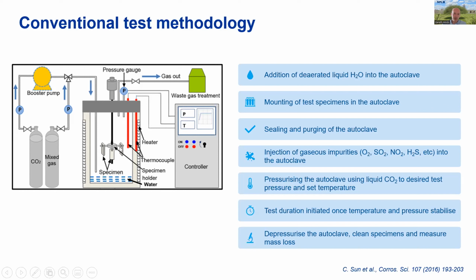You purge the autoclave. It's really important to remove all of the oxygen because oxygen is an alternative cathodic reactant in the corrosion reaction. You want to minimize that level because there is very little oxygen in the stream in service. Then the gaseous impurities are injected in a controlled manner. The autoclave is then raised to the pressure and temperature of the test. Then you maintain those conditions for the duration of the test, which can be anything from a few hours to several days or weeks. And then finally, the autoclave is depressurized.